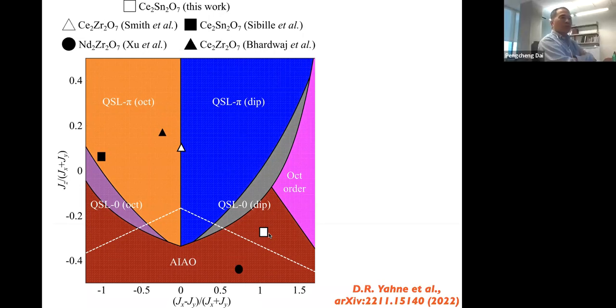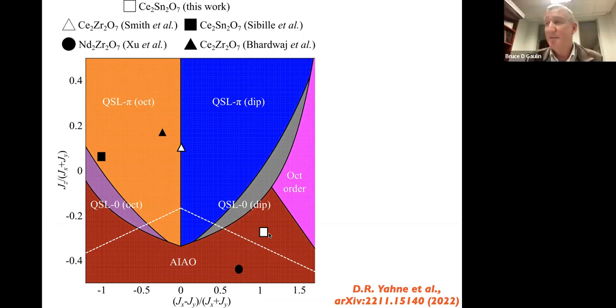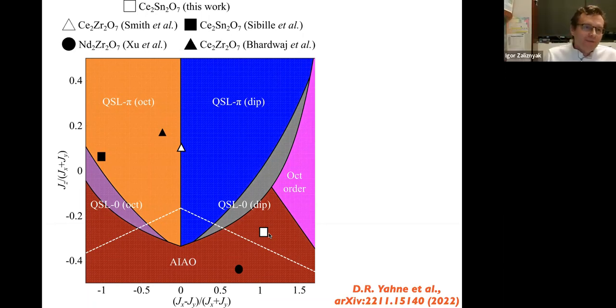But one way, Bruce, you can solve this problem is by turning on the magnetic field, right? Because if your hypothesis is correct, if the dipolar interaction, then you should really see spin waves, right? No, you should not see the spin waves if this hypothesis is correct, of course, because you see no spin flip if you have Jx and Jy equals 0. So they are totally dark.